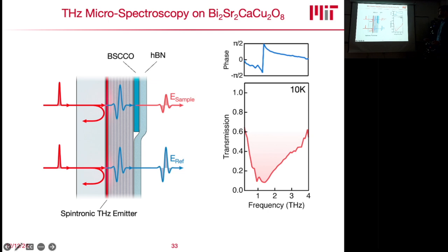Since we're doing a field-resolved measurement, we get amplitude and phase. So also of the transmission of these FFTs, we get amplitude and phase. And especially here in this depression, you suddenly get an almost perfect jump of pi in the phase of the transmitted terahertz light. Below the resonance, you have a minus pi half phase with the driving field, and above you have a pi half phase difference with the driving field. So this is already very interesting; this depression in the transmission is very, very important.